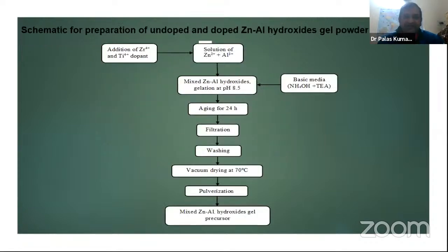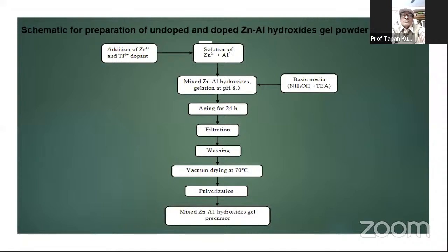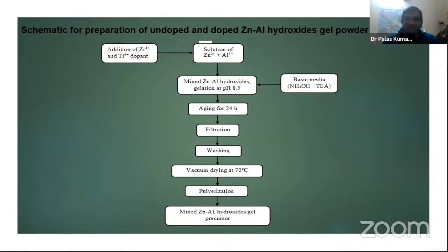So this is the schematic of the preparation of doped and undoped hydroxide gel powder. We already mentioned that we followed the co-precipitation route, where we chose the aqueous system, and in order to maintain the basic media, we used 1:1 ammonia with triethylamine, and the pH was maintained at 8.5. In these experiments, we used aluminum nitrate nonahydrate and zinc nitrate hexahydrate, AR grade with purity above 99%. For zirconia doping, we used zirconium oxychloride, and for titanium, we used titanium tetrachloride, right? One point is noted: titanium tetrachloride is a bit explosive in nature, but in order to avoid agglomeration in aqueous medium, in this experimentation we purposefully used titanium chloride, but it can be easily substituted by other available material.